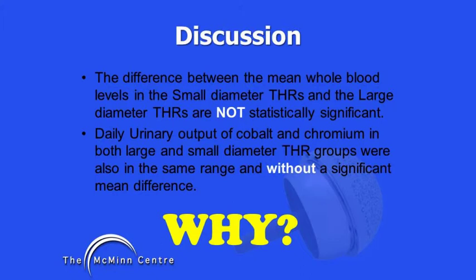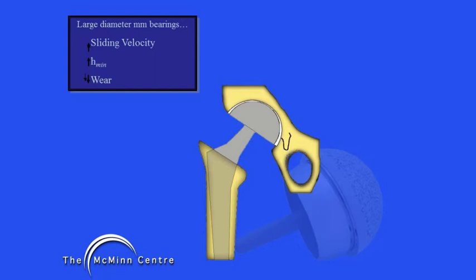Why is this so? Tribological theories suggest that by increasing the bearing diameter, you increase the sliding distance of the surfaces, which in turn enhances the sliding velocity of lubrication fluid, and benefits from a fluid film between the bearing surfaces, thus reducing the wear. However, when you look at the literature, you get a different impression.